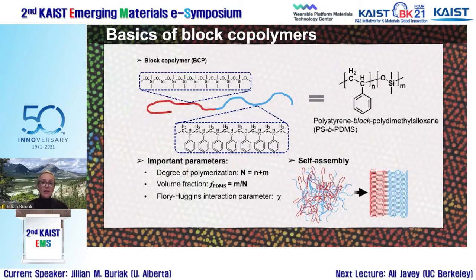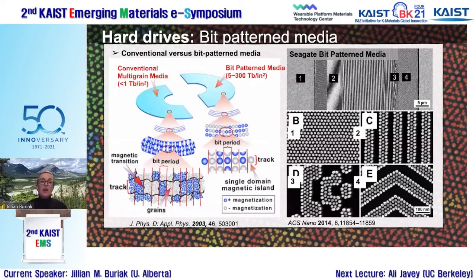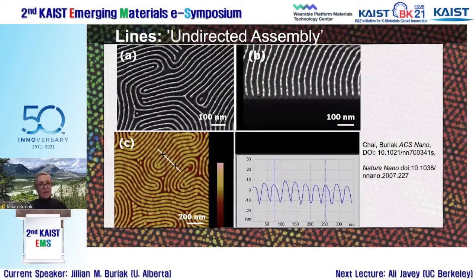And so where this has seen the most attention in the semiconductor industry is for hard drives, bit patterned media. And so that's why IBM and Seagate and others have been real leaders in this field. And so the idea, again, is using block copolymers that can then encapsulate single magnetic domains that could then be used as an easy way to literally almost slosh on a block copolymer onto a substrate, and that could then be used as hard drive media. So that's where the molecules, again, are doing the hard work for you to pattern and space out these magnetic bits.